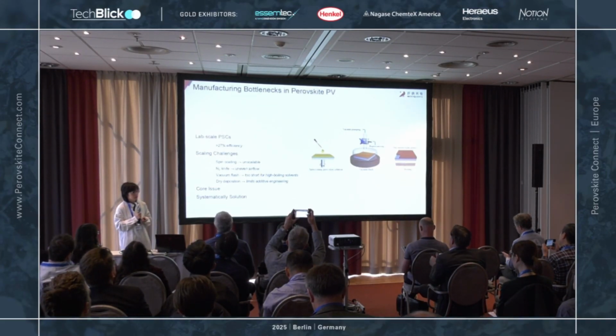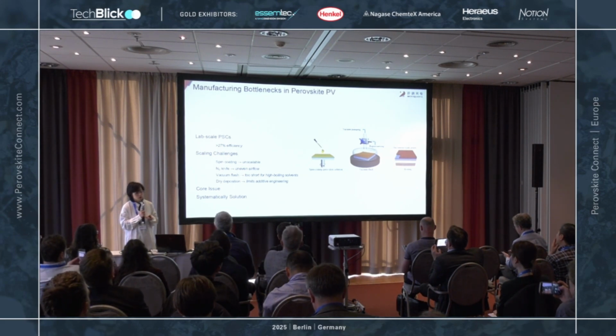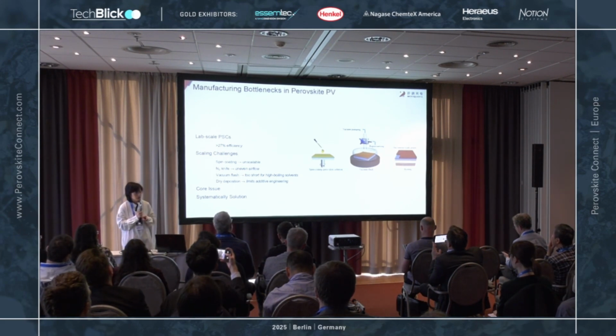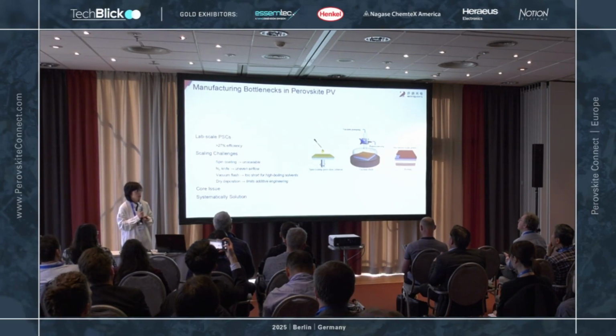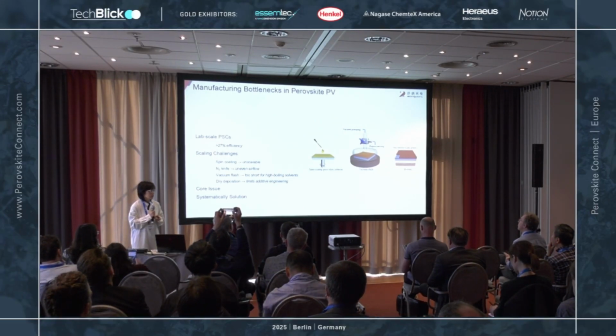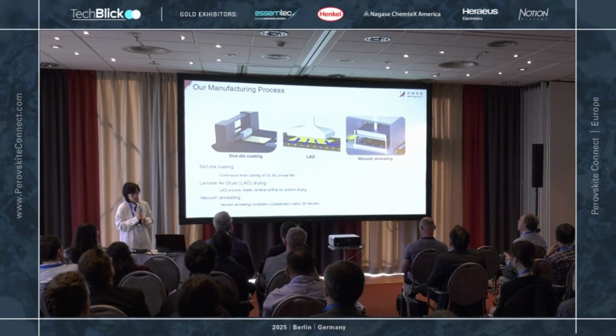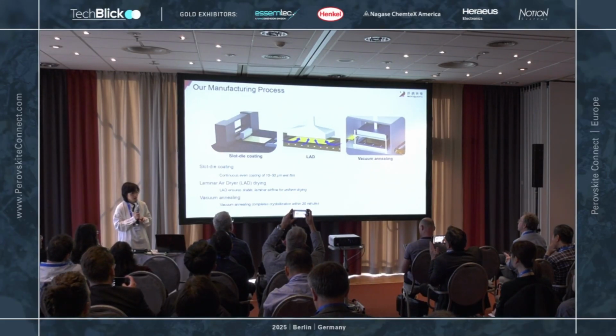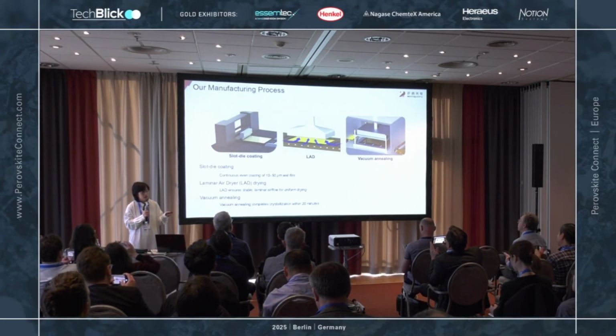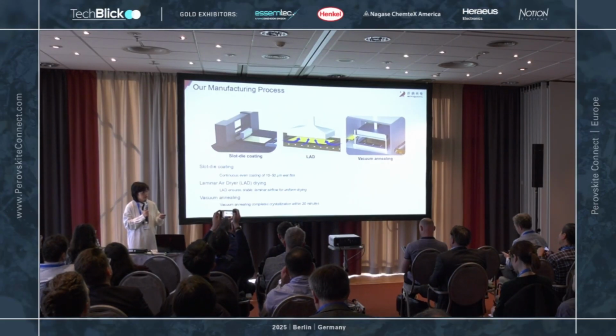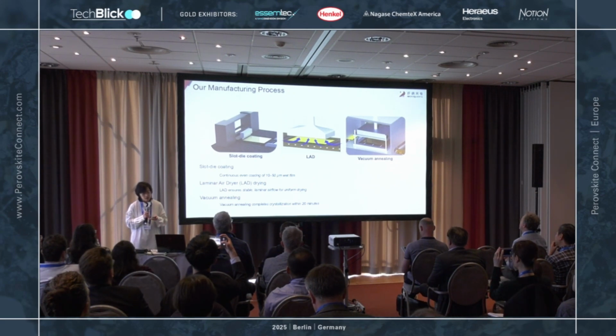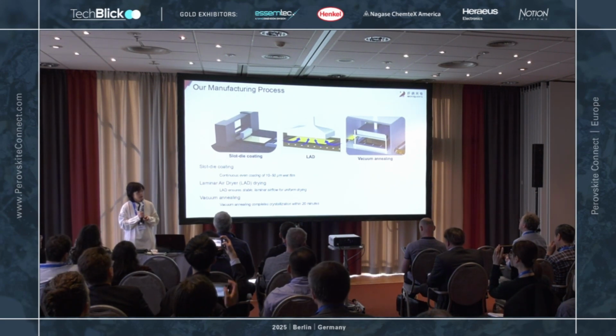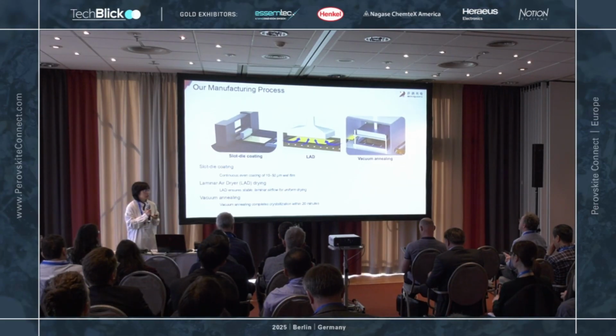We all know that in the lab, perovskite solar cells have achieved more than 27% efficiency, but when it comes to scaling up, we really have challenges. At Microquanta, we tackle this problem systematically by developing equipment and processes. This is how it actually looks in our production line. First, the substrate goes through the slot die coating process to create an even film, then through the laminar air dryer, the light drying process, and finally the vacuum annealing process at about 20 minutes to finish the crystallization and lock in the stability.